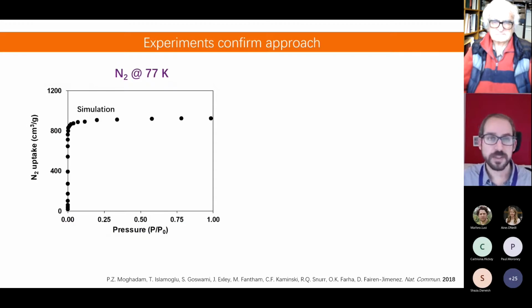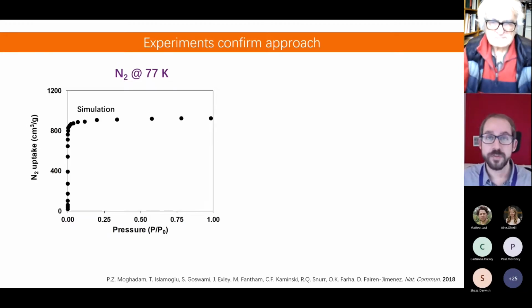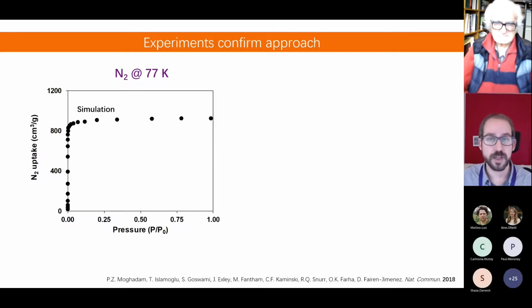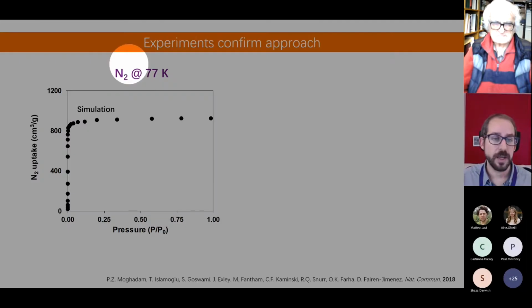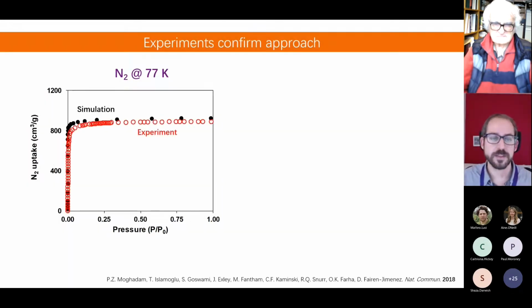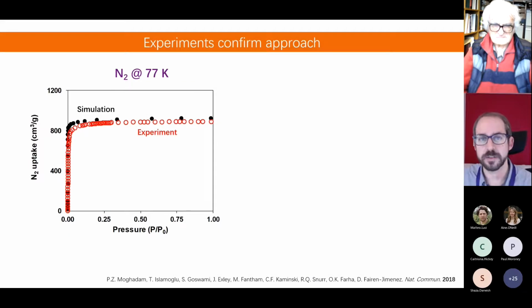We also prove that all the simulations are confirmed with experiments. This is the nitrogen isotherm that we measured at 77 K to evaluate the quality of the material. Nitrogen uptake as a function of the pressure, the simulation, and the experiments. You can see that we have a really nice match here. This means that we are able to predict the quality of the structure. The quality of the structure experimentally is very, very good. And this means that the experimental data matches with what we were simulating.